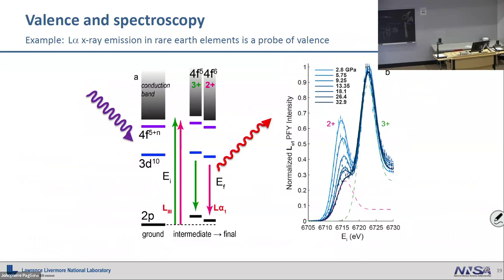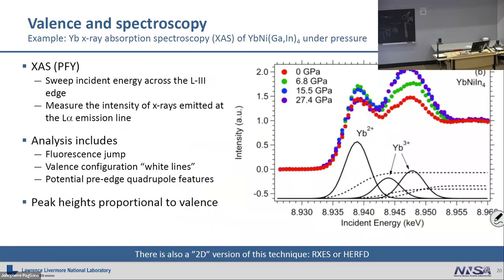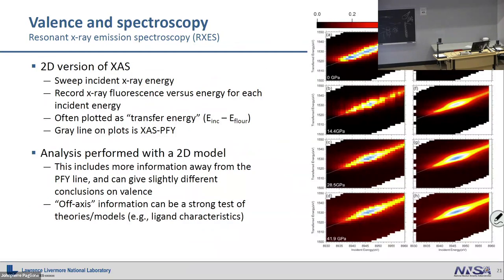I don't think I have a plot of that. Oh, I will. So this is what you would get out of the partial fluorescence yield. The first one I said, this is a single detector. For things like rare earths, this is great because you can tell the valence of the rare earth because the splitting between the 3+ and the 2+ is large. It's larger than the core hole lifetime broadening, so you can easily resolve the peaks and say, I've got samarium and it's 2.5. It's got some 2+ and some 3+ characteristics. Or ytterbium like this.